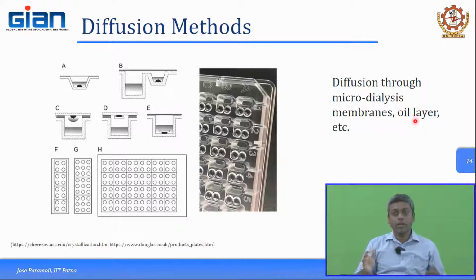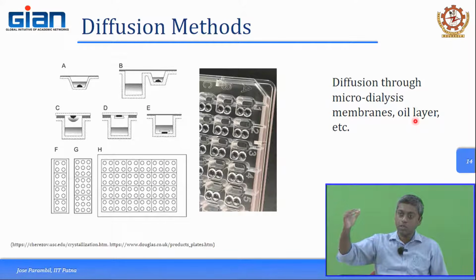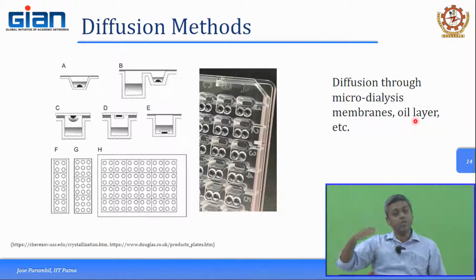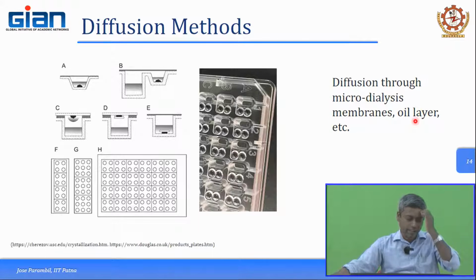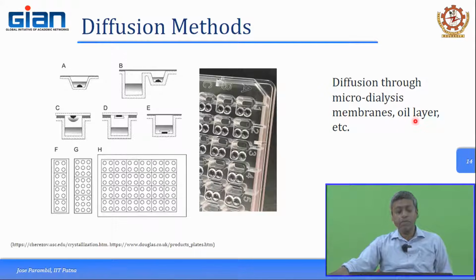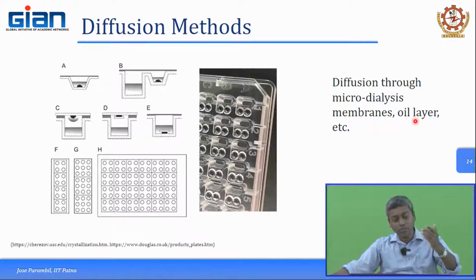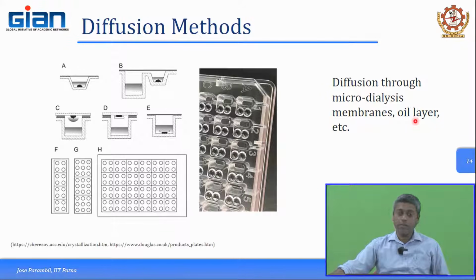But of course, even though we say that oil and water are not miscible, still a very small quantity of water might be miscible into oil, and that quantity might mix with oil and evaporate from the other surface, leading to a very small rate of evaporation. So, that is also another way to control it without going for these other techniques, or as mentioned, the dialysis membranes, which are selectively permeable only to the salts, let us say. That would also help to make the concentration gradients very gradual, in order to give enough time for the nucleation to happen.